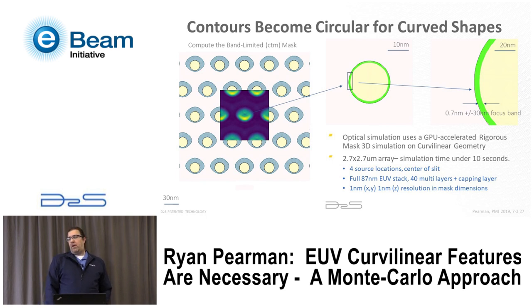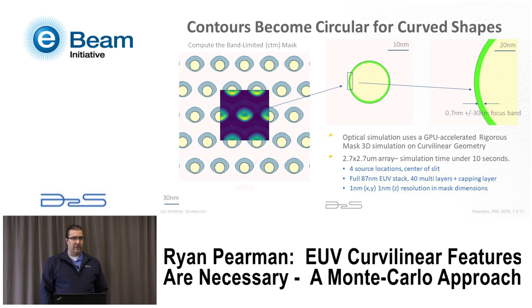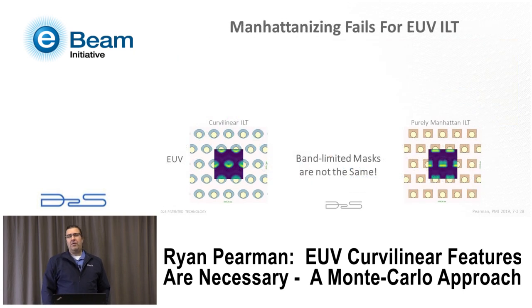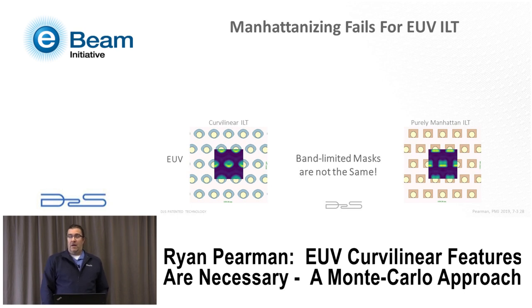I'm not making approximations in this optical system — I'm doing a real rigorous 3D EM calculation using a highly GPU-accelerated system where we can do almost a 2.7 by 2.7 micron array with four source points in under 10 seconds, which is incredibly fast. Looking at the continuous tone mask, you'll see there isn't the same band-limited mask between the oval and the rectangle. Some of this is due to the wavelength effect, but a lot is due to the chief ray angle effect of 6 degrees as well as the mask 3D effect.